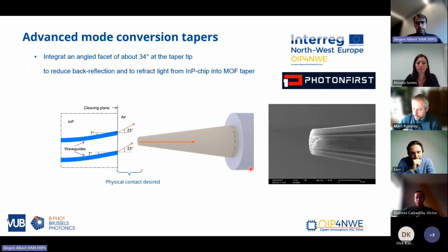And then with Photon First, finally, we've been looking at advanced versions of these mode conversion tapers. So in the indium phosphide PICs, you often see that the waveguides are coming to the edge of the chip under an angle. And of course, that means that you would either have to position your fibers also under an angle, which then complicates the packaging, again, especially if you want to connect more than one fiber, or in other words, arrays of fibers, because then you would at some point just hit the chip.